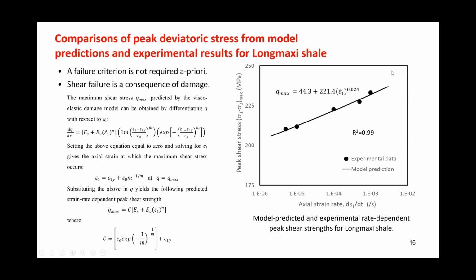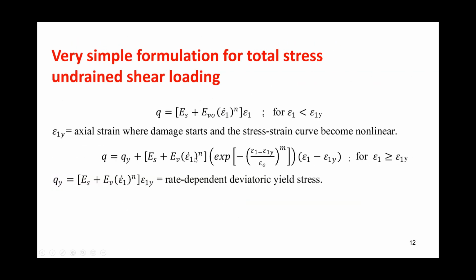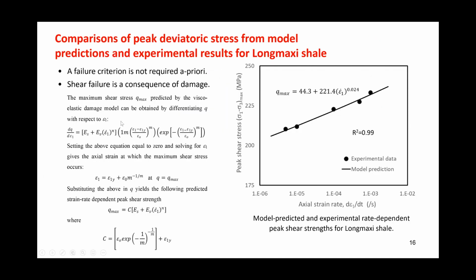One of the things about the model you will notice is that I did not prescribe a shear failure criterion. I did not prescribe it because it is an outcome of the damage formulation. So a shear failure criterion is not required. If we differentiate this stress-strain relation, the bottom one, Q versus epsilon_1, with respect to epsilon_1, we get this derivative. And if we set this to 0, we get the actual strain at which the peak is going to occur. And the peak is the shear strength.